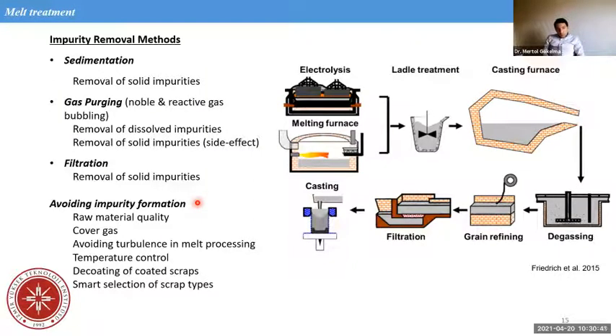In addition, of course, removing is important, isolation, removing of any impurities, but avoiding impurity formation is sometimes more clever. The parameters which help us avoid impurities are firstly the raw material quality, which is not very easy to control, and the cover gas to decrease the oxidation, and avoiding some turbulence in melt processing, because as I already mentioned, aluminium oxide is a stable oxide and it forms a stable protective oxide layer on the melt, but it cannot protect if you have turbulence or disturbance of the melt. So we avoid turbulence as much as we can. Casting people know it better, how carefully they cast products into the molds to avoid any turbulence.